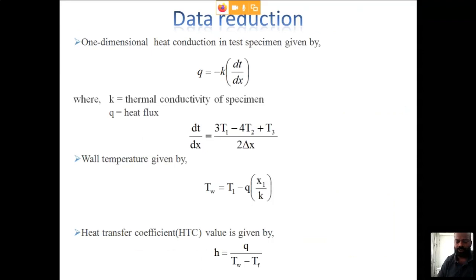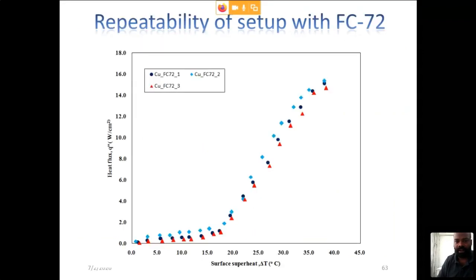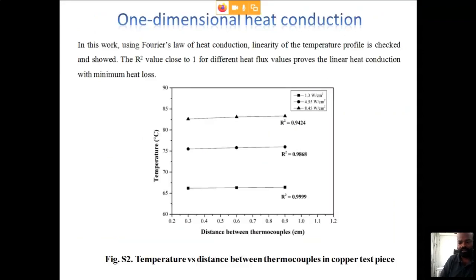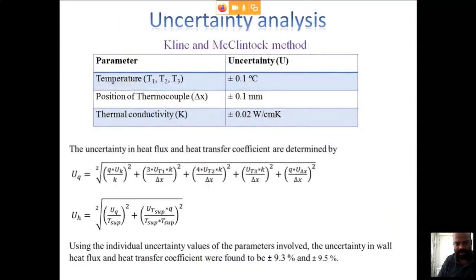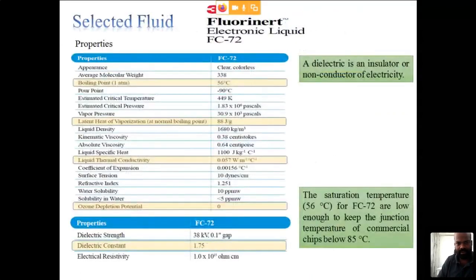Now, as you saw, pool boiling heat transfer is all about measuring the heat flux and the temperature value, the surface superheat value. The methodology to calculate these two values is given here. I don't want to go into these aspects. You can see I have done the repeatability test, the heat loss test, uncertainty analysis, and we have used the FC72 dielectric fluid to act as an immersion cooling liquid.